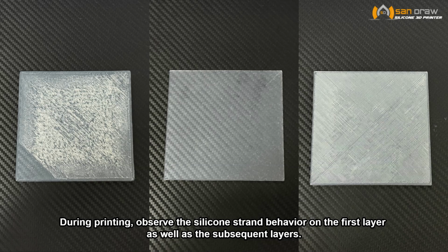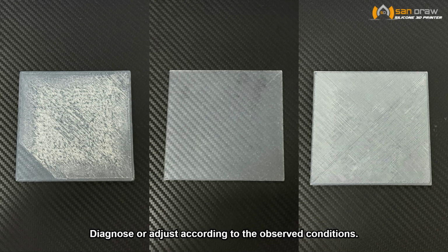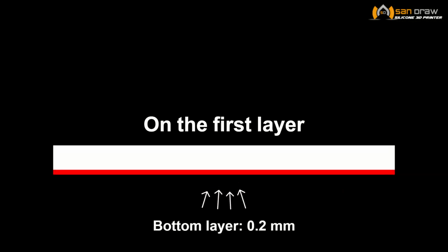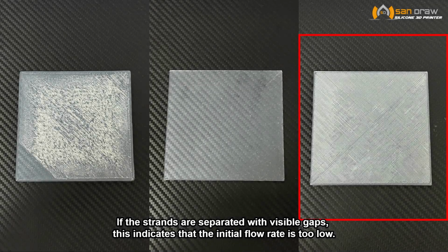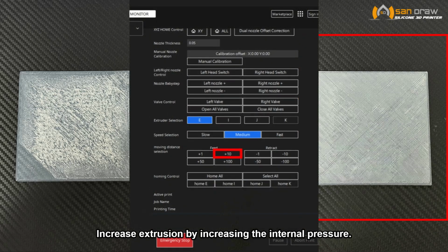During printing, observe the silicone strand behavior on the first layer as well as the subsequent layers. Diagnose or adjust according to the observed conditions. On the first layer, if the strands are separated with visible gaps, this indicates that the initial flow rate is too low. Increase extrusion by increasing the internal pressure.